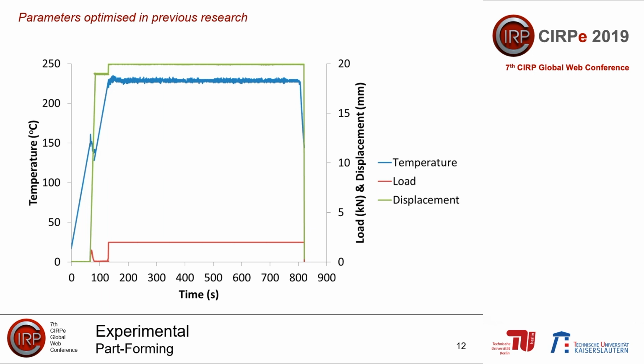Our thermomechanical cycle, these parameters optimized in the previous research. Heating rate 2 degrees per second to the forming temperature of 150 degrees. Stroke displacement rate 1 mm per second to forming depth of 95% of the complete stroke displacement. Resume the heating rate of 2 degrees per second to the dwell temperature. When we reach the dwell temperature, we complete the final 5% of the forming. Dwell conditions 230 Celsius for 600 seconds, and then die cooling at 60 degrees per second.